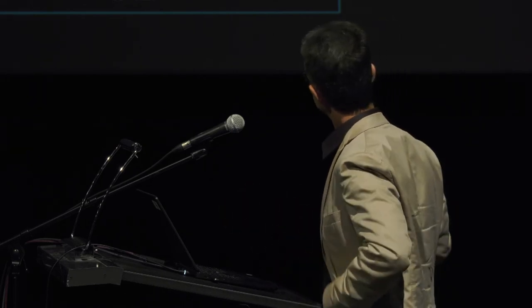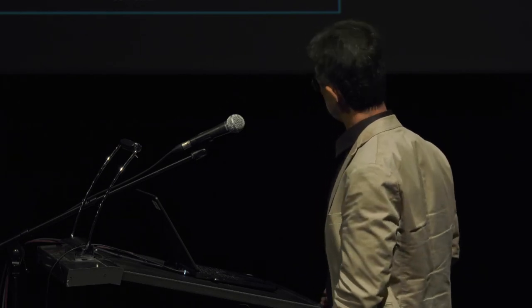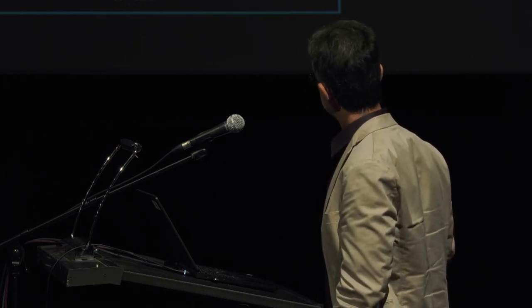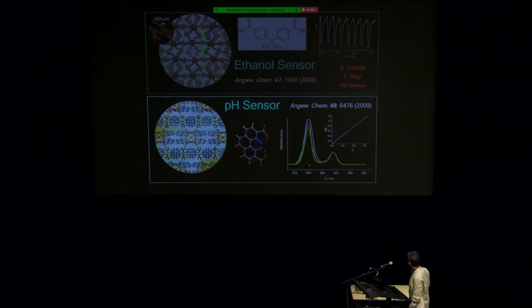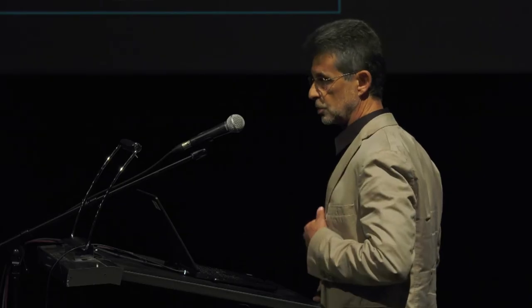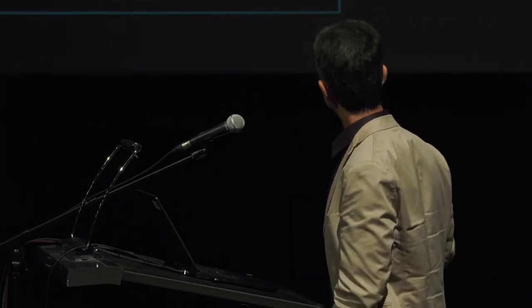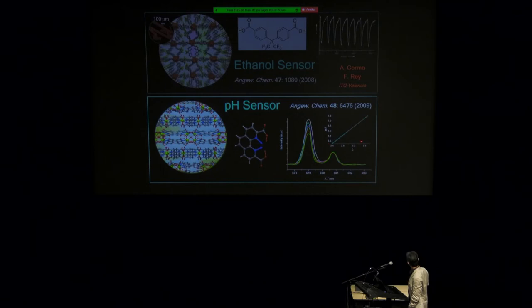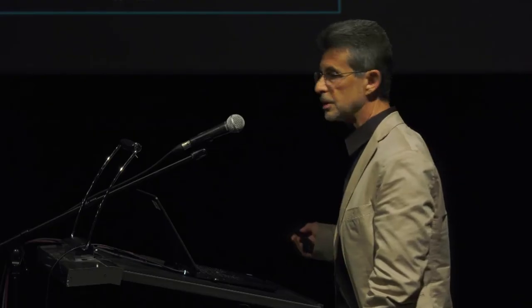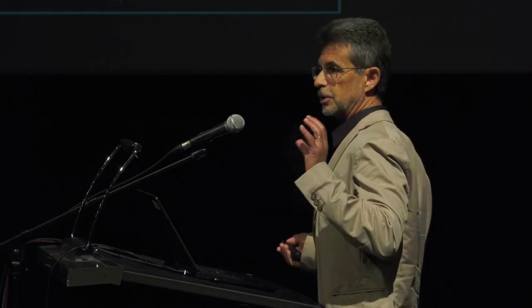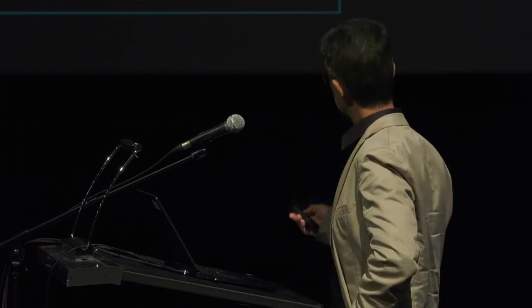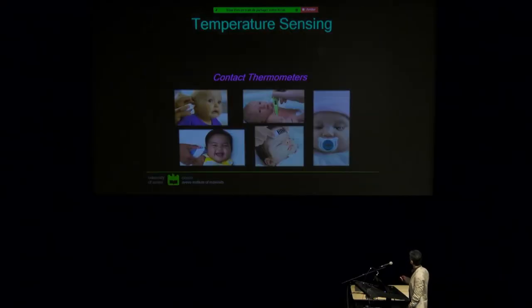And so if we measure fluorescence, this is just an expansion of the emission spectrum. What you see as a function of pH is that this band changes, while this band doesn't change, because this comes from the monomer, which has no water molecules or OH groups in the vicinity. And so if you plot this, you get a straight line in the pH range of biological interest. So this is a self-calibrated pH sensor based on an organic and inorganic hybrid.